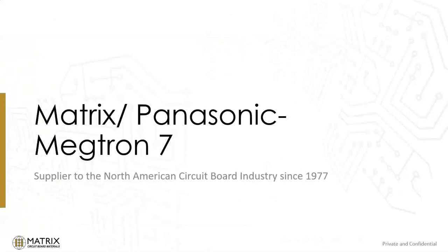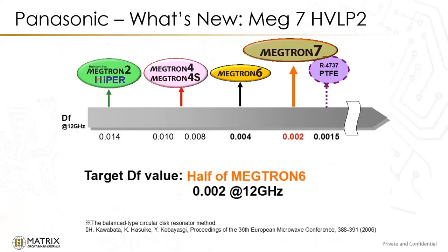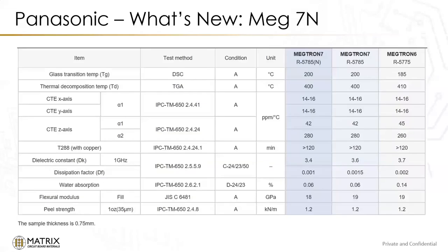MEG 7, that's the next generation. We're talking about high performance. When it was conceived, the idea was for MEG 7 to be half the loss of MEG 6, be higher performance. So you can see the target here, 0.002 at 12 gig for the loss factor. So it's approaching PTFE, but much better than MEG 6. There's also a low Dk glass option, 7N, and that seems to be where a lot of the activity is when we're going for higher performance from MEG 6, going from MEG 6 to 6N, and we'll talk a little bit about that in some of the charts here.